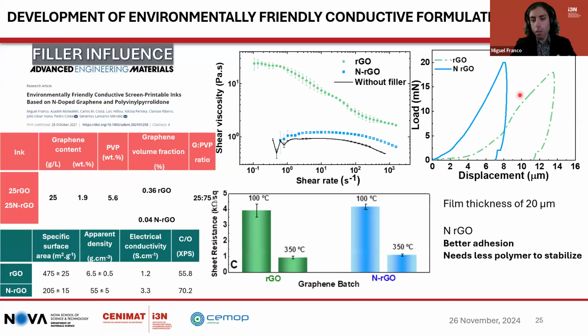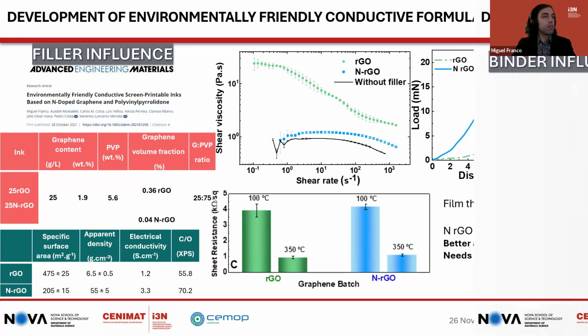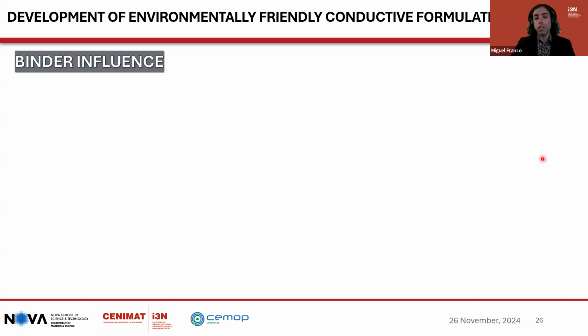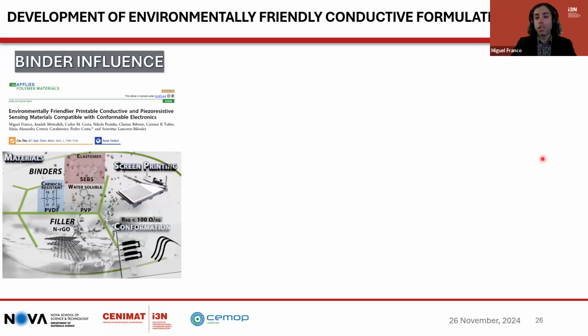nitrogen-doped graphene. Moreover, due to its higher specific surface area, reduced graphene oxide needs more polymer to stabilize it, hence having a worse adhesion than nitrogen-doped graphene. For those two reasons, nitrogen-doped graphene was selected for the next study, in which the influence of the binder was studied.